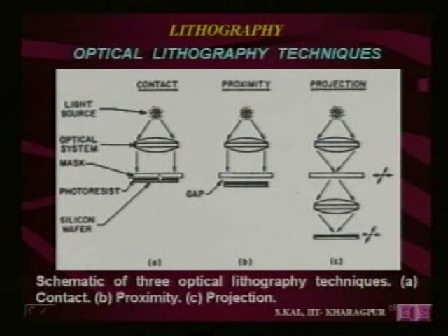Okay. So now, when the alignment is satisfactory, the next step is exposure of the photoresist film using the ultraviolet light. The exposure time we decide by standardization, which has already been done. When satisfactory alignment is achieved, we expose the wafer. In this collimated beam there is a shutter arrangement. If we press a switch, the shutter will open, and this parallel beam of UV light will be exposed on the wafer, and after a certain time the shutter will automatically close this path. A timer is also there, and you can set the timer beforehand so that we can expose for our desired time.